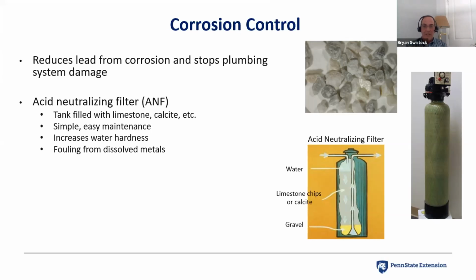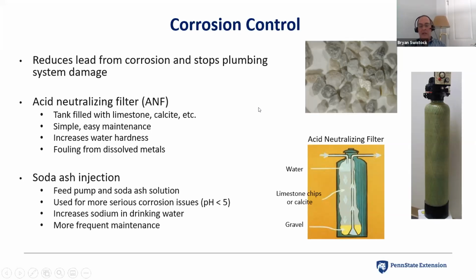I hate to see that because you have two treatment devices that are fighting each other, and you really don't want to get into that, but we do see cases where that happens. There can also be problems with these if you have metals in the water. It may foul up the bed of material you have because you're starting to oxidize some of the metals out, and they'll start to coat the alkaline material, and you'll start to reduce the effectiveness of the corrosion control that you're getting from the filter.